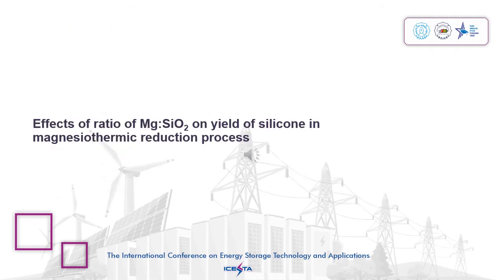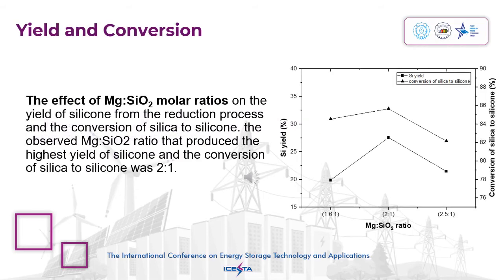Next result, the effect of the ratio of magnesium and silica on yield of silicon in the magnesiothermic reduction process. The effect of magnesium and silica molar ratio on the yield of silicon from the reduction process and the conversion of silica to silicon. The observed magnesium and silica ratio that produced the highest yield of silicon and conversion of silica to silicon was 2:1.